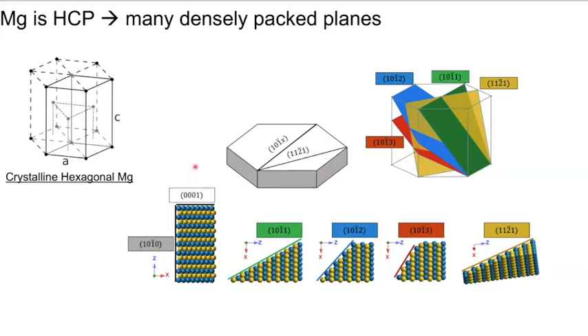And in magnesium, the most thermodynamically stable facet is the basal plane, 0001. You might notice an extra index here because we are in the hexagonal system. The third index is actually redundant with the first two, but that's the notation, all right? And then there are a number of other facets, not quite densely packed, but quite packed. So the 0001 is close packed. The other ones are, let's say, less packed.